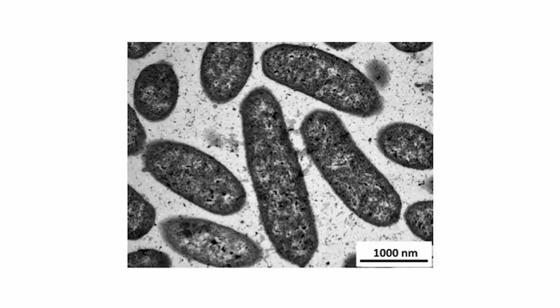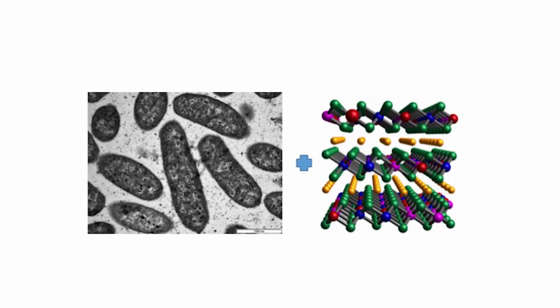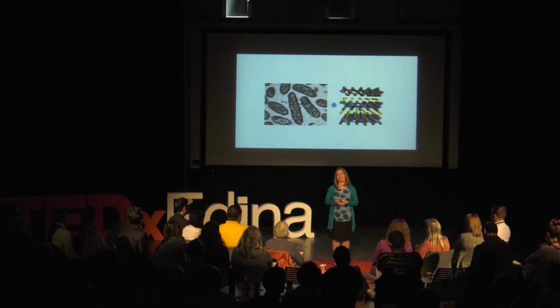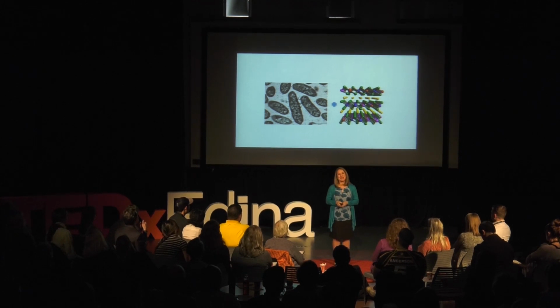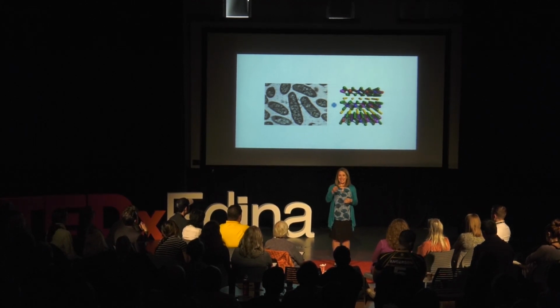So we did systematic experiments where we exposed our Shewanella to our nanoscale nickel manganese cobalt oxide, or NMC. And I'll tell you, our initial hypothesis was that those nanoscale sheets were going to cut through the bacterial membranes like a nanoscale knife, decreasing bacterial viability. In fact, that's not what we saw at all. There was no sign of them cutting into the membranes.